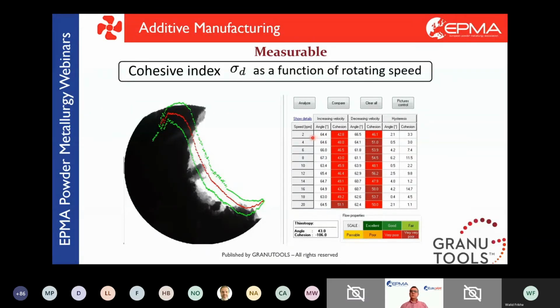What we can see is that the cohesive index is a function of the rotating speed. If you measure it at 2 RPM or 20 RPM, you don't get the same value, which is logical because the goal of the characterization is to comply with the process condition. Depending on the speed of your recoater, you won't gain the same spreadability. Depending on the speed of the rotating drum, you won't get the same cohesive index. This is reassuring because we can tune the speed of the rotating drum to match the recoater speed and have a very close proxy to the process.